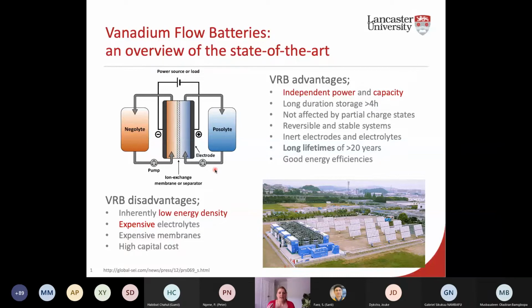So the vanadium flow battery, in terms of it being the state of the art, is really the benchmark for where the systems that we're developing now need to compete. And it has the advantage of having that independent power and capacity because everything's dissolved in solution. It offers that long duration energy storage. And it's also not affected by partial charge states, or by small boosts of charging suddenly going back to discharging or being left in a resting state. It's very flexible and adaptable to unpredictable bursts of energy and extractions of energy, as you would expect on a grid-based system.